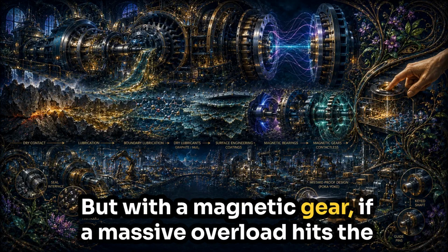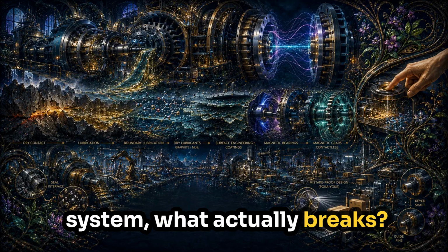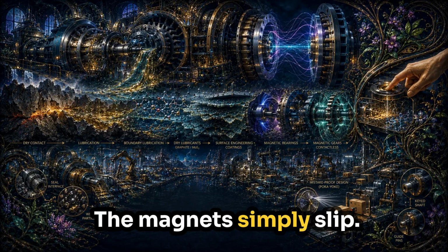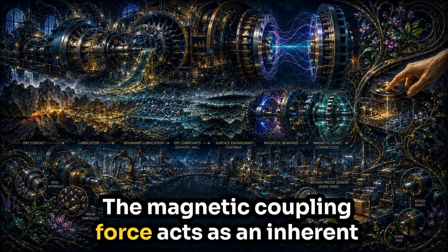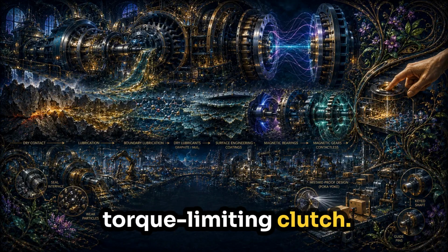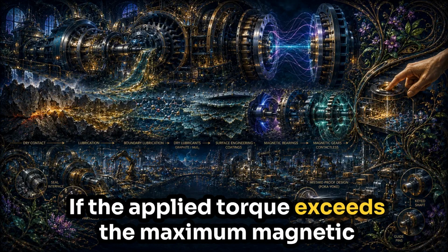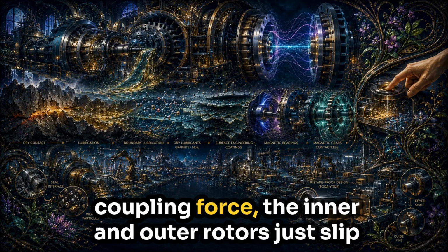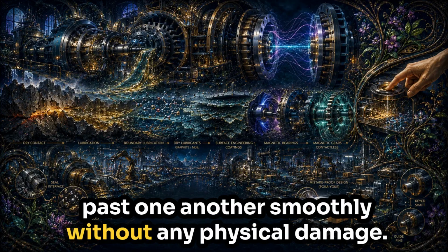But with a magnetic gear, if a massive overload hits the system, what actually breaks? Nothing breaks. The magnets simply slip. The magnetic coupling force acts as an inherent torque-limiting clutch. If the applied torque exceeds the maximum magnetic coupling force, the inner and outer rotors just slip past one another smoothly without any physical damage.